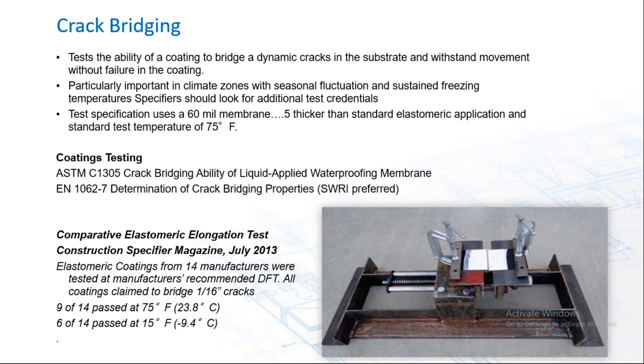There is ASTM C1305, a pass-fail test that provides test results at two temperatures, freezing and at normal 75 degrees Fahrenheit room temperatures, excuse me. And again, the test procedure can be modified to suit an individual's ends.